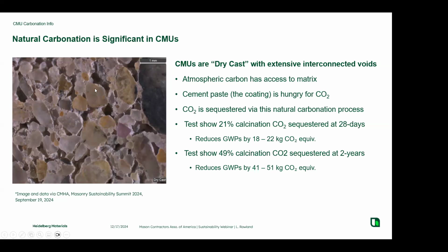So each one of these little bits of rock and sand, here's probably a rock you can see, this is 1 millimeter. And then also all these little bits of sand are all coated with cement paste. Well, as you can see, the outside is where that paste resides. And as the atmosphere, as the CO2 enters the system, it recombines with the available calcium. Calcium doesn't like to be left alone. It wants to combine with CO2. And so we've basically recarbonated the calcium associated with that